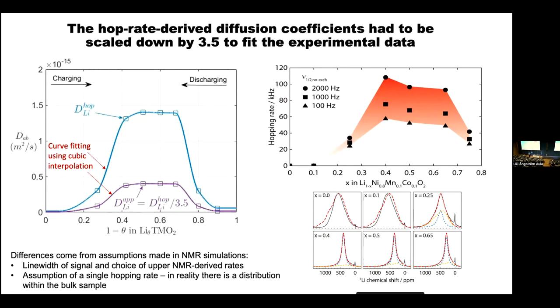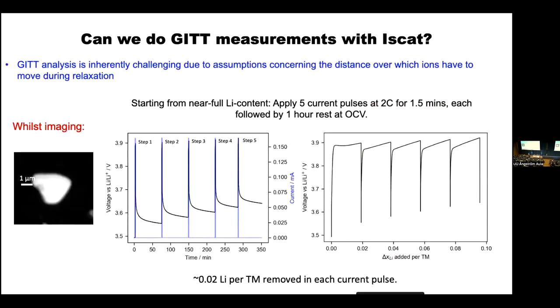What these continuum models do in combination with iSCAT is really allow you to get the diffusion coefficients at the single particle level. I just want to show you some preliminary experiments where we're trying to explore that in more detail. We're trying to do GITT, galvanostatic intermittent titration experiments, in iSCAT. Those of you who do this analysis know that it's very difficult to get the diffusion coefficients from that method. You get an apparent diffusion coefficient that depends on your assumption of how fast the ions have to diffuse after you've given the constant current pulse.